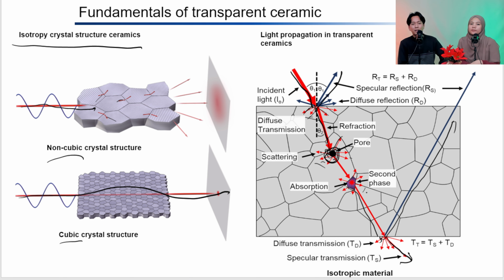So it's very difficult to use a non-cubic ceramic structure as transparent ceramic. Although there are some, like quartz for silicon dioxide and sapphire for alumina, they should be fabricated into a single crystal material to be highly transparent. That's why it's generally easier to use cubic ceramic for transparent ceramic, because it's cheaper and simpler to fabricate.